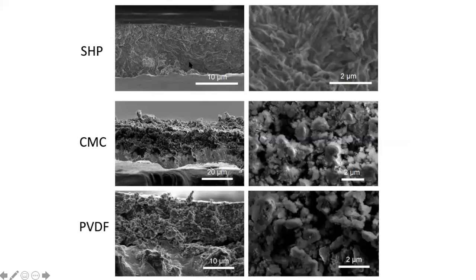And then we also looked into the battery electrodes after charging, discharging many times. This is a scanning electron microscopy image of the electrode. After charging, discharging 100 cycles, we take apart the battery, and then we take the electrode, just break it, and look at the side view, the cross section. What you're looking at here is particles together with the polymer. After charging, discharging, the shape of the particle already disappeared. It just becomes this very dense layer.